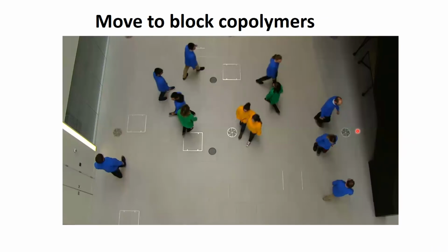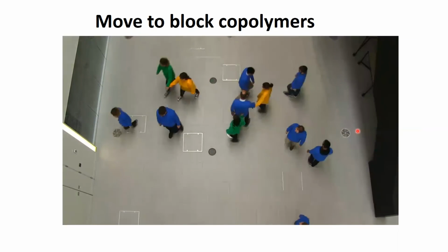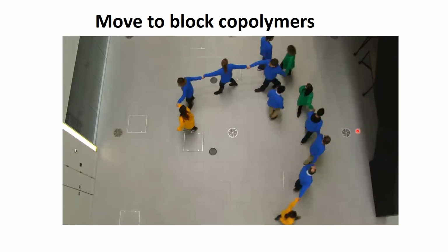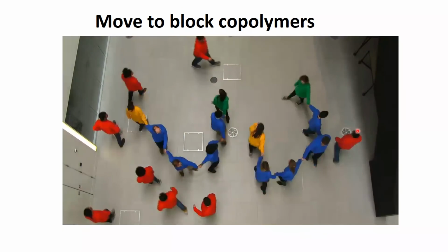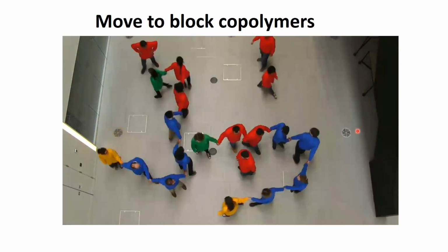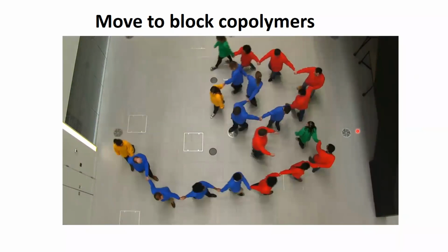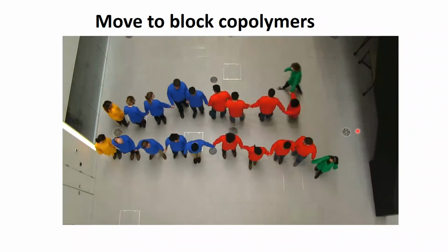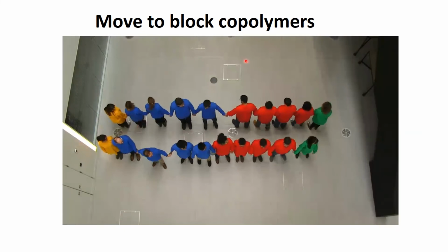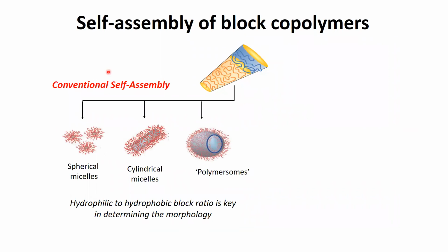So we need to go to block copolymers, and the way that we do that, where we use again our controlled radical methods, where we have a capping agent in green, we add monomer units, the blues polymerize, then we add in a second group of monomers, which are now the reds. The reds keep adding to the end, and hopefully we will end up with two chains that now have a blue part and a red part. And the key thing is these two segments don't want to interact, they phase separate, and we can use that phase separation in something called self-assembly. And this is what nature uses to build a lot of its constructs. So this self-assembly essentially allows us to make all these different types of shapes. And the size of the blue polymer compared to the red polymer basically determines what shape we get. We can get spheres, we can get rods, we can get hollow spheres.